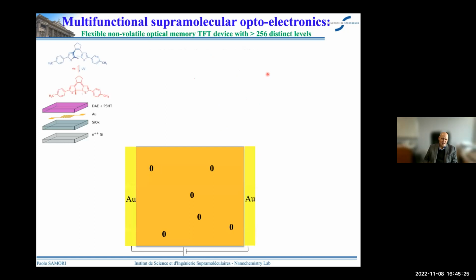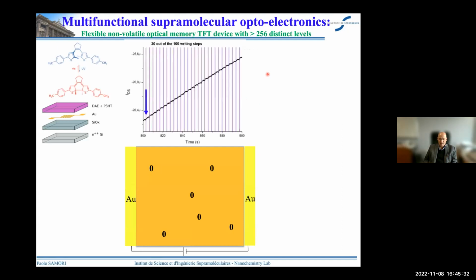And so the idea is, again, we go to the cartoon I showed you before, a bottom contact, bottom gate transistor. In the channel, you have a blend of P3HT with the diarylethene. And now here, if you use a low power and ultrafast laser, each pulse, there is a finite number of diarylethene molecules that undergo isomerization from the open to the closed state. And so we are creating a finite number of traps. And that's what you can see here, that each pulse, you have a stepwise decrease of the current through the junction. And so you can see that each pulse, you have an increased number of closed isomers that appear, and this is reflected by lowering of the current through the junction. And this allows us to make over 256 distinct levels, which correspond to 8-bit memories.